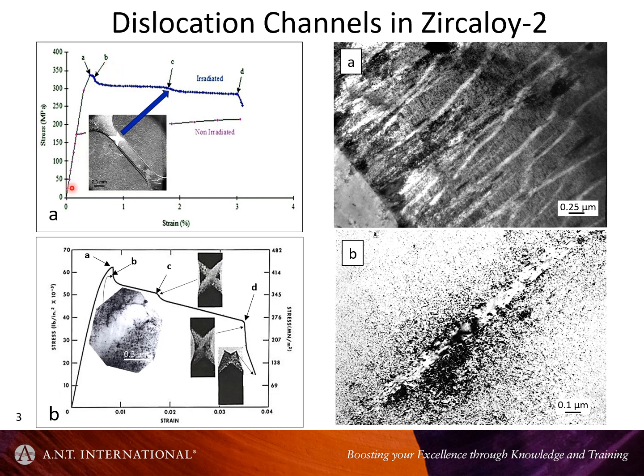And this is a stress strain curve. You see the non-irradiated part here, and then this is the irradiated part. So what irradiation does, it increases the yield strength and the ultimate tensile strength. And then when you deform, when you eventually start to form these channels, you get a load drop, and if you follow the stress strain curve along, at some point, often you get a second load drop, and that would be because of the secondary slip systems that start to become initiated.